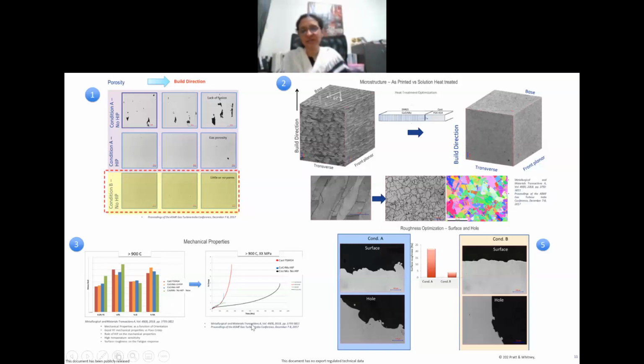And we evaluated the creep, the low cycle fatigue, high cycle fatigue, thermomechanical fatigue. Since it's a high temperature part with the thermal barrier coating, we added a thermal barrier coating. So what I'm summarizing for you in challenge number 3, it's definitely a challenge. You need to pay some attention to it. Not only to the properties of uniaxial tensile or compression or creep, but also to whatever the property demands. Let's say if it is a wear application, like I showed you in the DED example where there was a wear, we went and did a fretting wear. So you don't need to reinvent the wheel, and especially now in 2022, where there's tons of literature available, a lot of people in the world are working in different groups. So given the proprietary nature, sign a non-disclosure agreement and get it. You don't really need to reinvent all the testing, because chances are it is available somewhere.